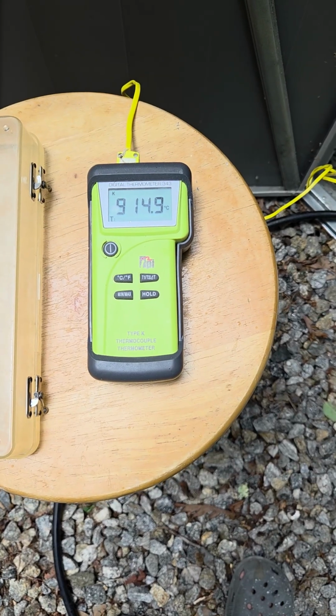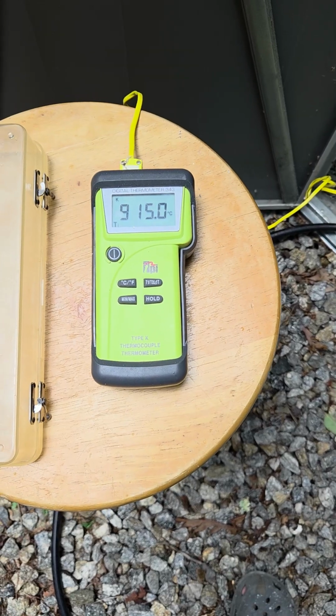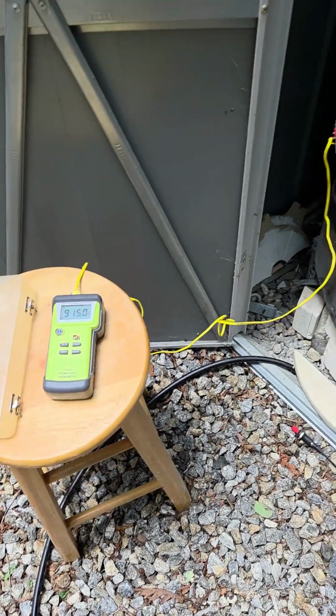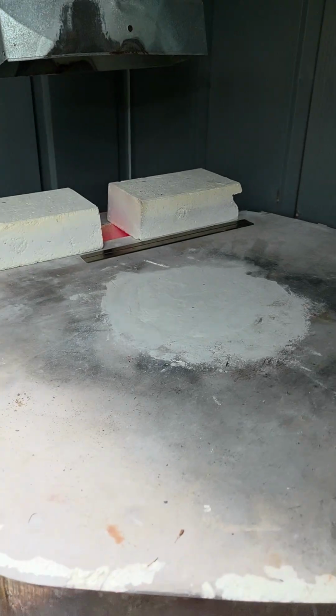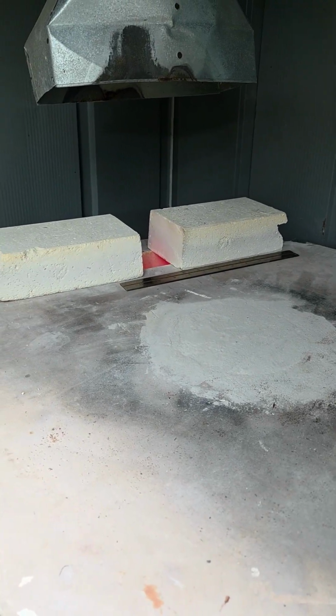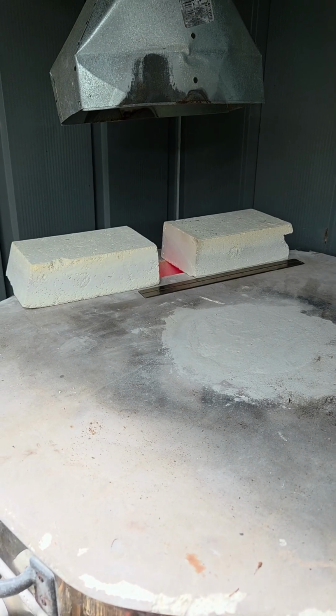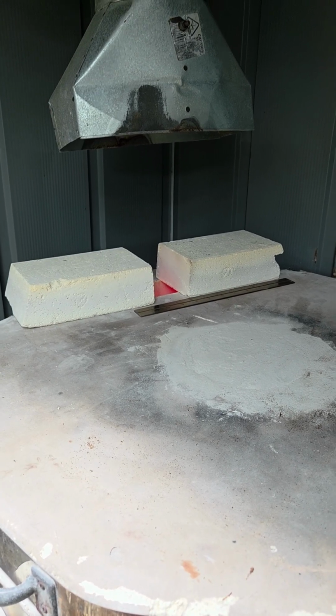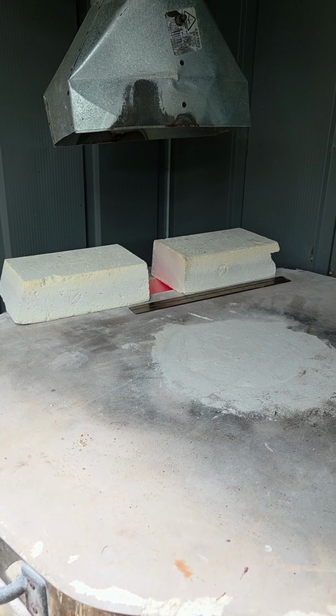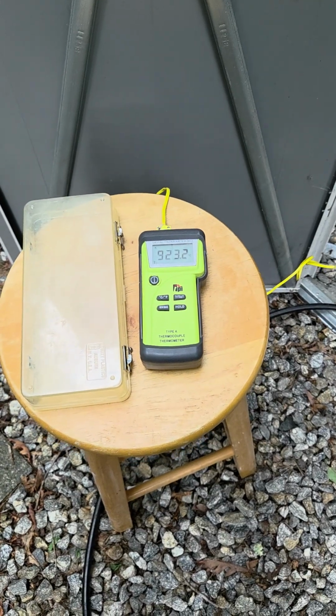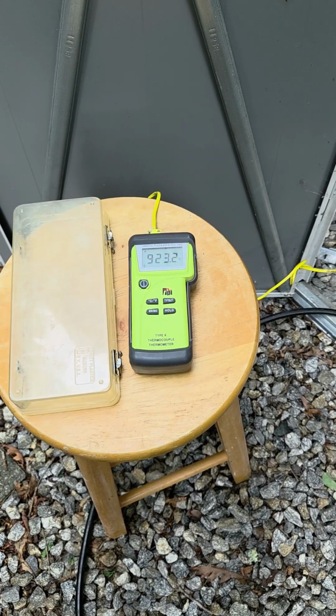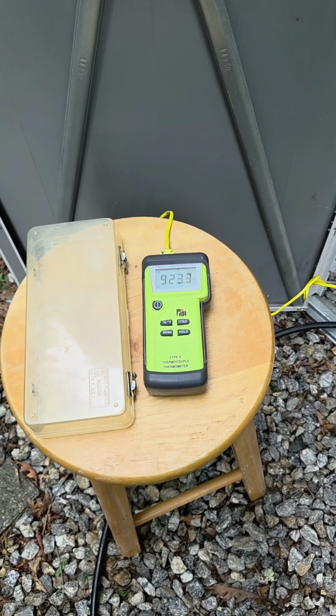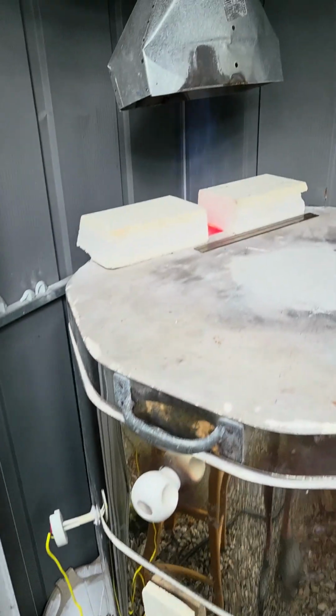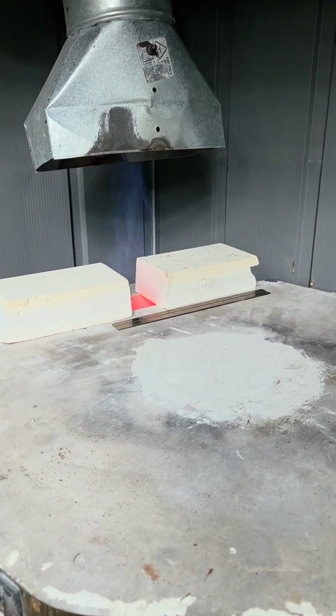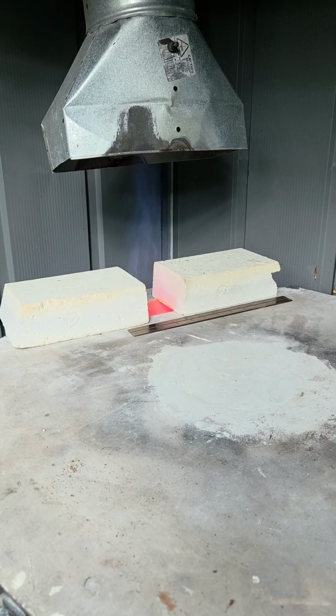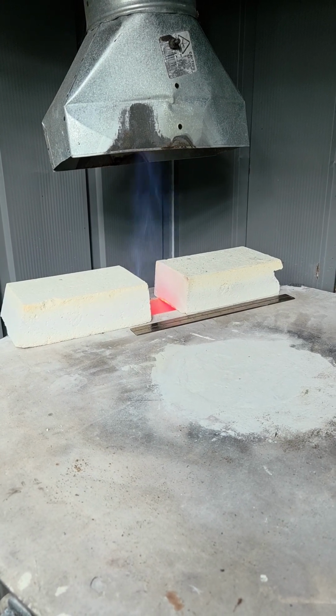So after about 10 minutes, it's gone up to about 915 degrees centigrade. I'm going to leave it there. I haven't changed the setting. Really no obvious reduction flame yet, but standing this close, I can smell a bit of an acrid smell, and that's the reduction. It's been in body reduction for about 25 minutes, and it's gotten up to 923 degrees. And all of a sudden, at that higher temperature, a reduction flame is now evident coming out of the flue.